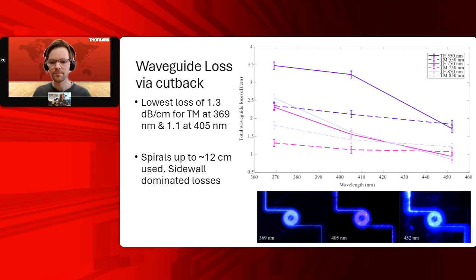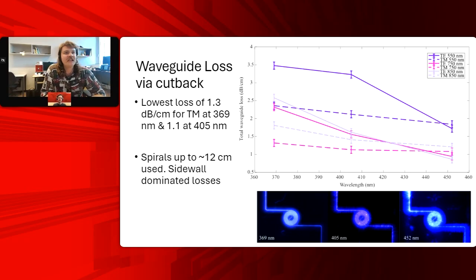That's a really good question. First off, as you see on this slide, I have TE and TM loss results, and they differ drastically for the same waveguide width and wavelength. That's because the sidewall roughness, this Rayleigh scattering, scales by lambda to the minus 4, which is such a problem in the UV realm. So currently, because we just use E-beam resist as the etch mask, we're inherently a little bit limited in the knobs that we can turn for sidewall roughness reduction. This is why we're looking at moving towards hard mask etching, and this hard mask etching can inherently pass less of this roughness to the next layer, that being the aluminum oxide, which is hard to do, right?